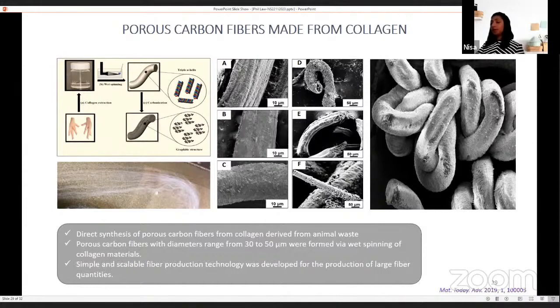So here is one of the outcomes of our research in this area. So together with CSIRO, we have successfully established sustainable and environmentally friendly methods to extract collagen from chicken byproducts. And we use that extraction to make carbon fibers, and we come up with highly porous carbon fibers. So these are the SEM images. So you can see that the fibers we created were very, very flexible. So in our approach, we use very environment friendly materials and processes to create opportunities in circular economy.